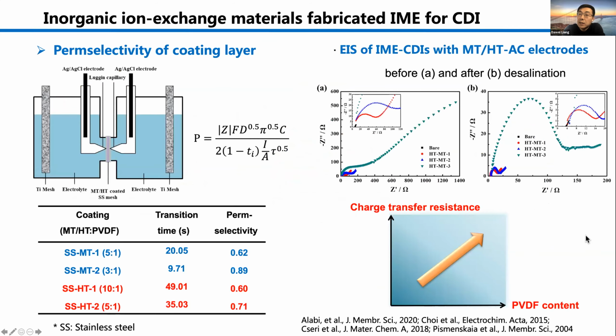We also investigated the permselectivity of the sole MT or HT coating layer painted on stainless steel mesh as a support substrate. And the results tell us that the higher the PVDF content, the higher the charge transfer resistance, but it could also get a higher permselectivity.